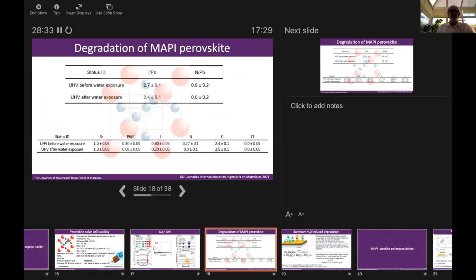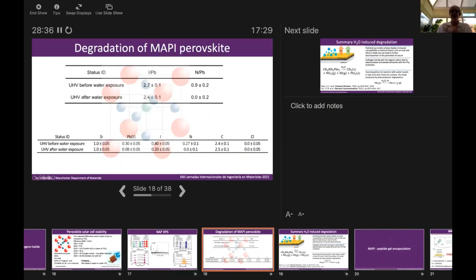We look at some numbers. We see for the iodine to lead ratio before water exposure is around 3, which is what you would expect. Remember, it's methyl ammonium lead I3. After water exposure, this value has dropped to about 2.5. The nitrogen to lead ratio for the pristine sample is about 1, and after exposure is 0. So it appears that the nitrogen is completely lost from the surface.